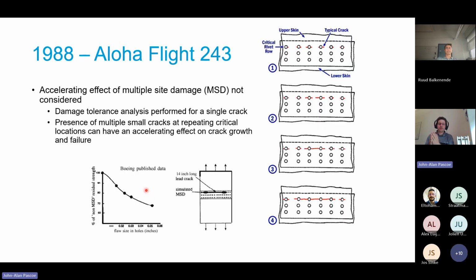As people started investigating it further, they realized there's this phenomenon called multiple site damage, MSD. And what happens is you have these small cracks, but they don't grow independently from each other, right? If you have a location with multiple holes, you might have multiple cracks starting, one at each hole. But as they grow towards each other, they start influencing each other, they start interacting, and they can even link up. And so you can go from 2 relatively short cracks to 1. Here you have a crack that goes from here to here, it's relatively short. But at the next stage, now you have a crack going from here to here, all in one go. Right? So your crack very rapidly gets much larger.